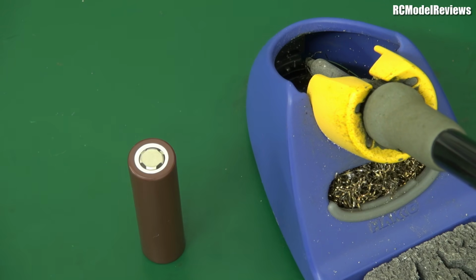Well, kill them immediately. If you get the old plumber's flux, which some people have done, and you put a bit on there, yeah, it'll get it really shiny, but as time goes on, the flux continues to corrode not only the battery, but the wire connected to it, and your wires will fall off. They'll corrode and fall off. So never ever use an acid flux. In fact, if you do this properly, you don't actually need any flux other than the flux that comes in your flux core solder.